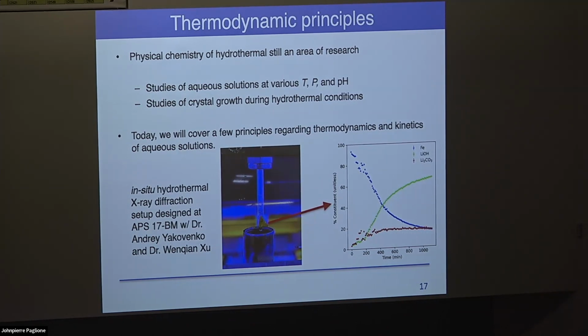The studies of crystal growth under hydrothermal conditions, as I mentioned, really started to take off with the use of synchrotron X-rays or in situ neutron diffraction, things like that. And you can actually try to study the kinetics of crystal growth using hydrothermal. This is an experiment that we helped design at 17-BM at Argonne National Lab, where we have a quartz tube filled with water and our reagents, and I'll show you more about this later. We take diffraction patterns every 30 seconds, and after refinement, we can plot the different constituents of a reaction, the products and the reagents, over time and see exactly the kinetics of how these metastable states form as a function of time. This was done over more than 1,000 minutes, a long-term scan on the X-ray system.